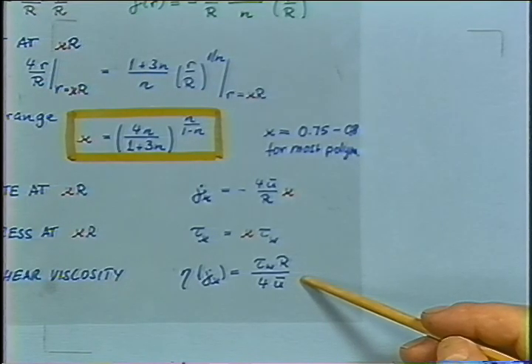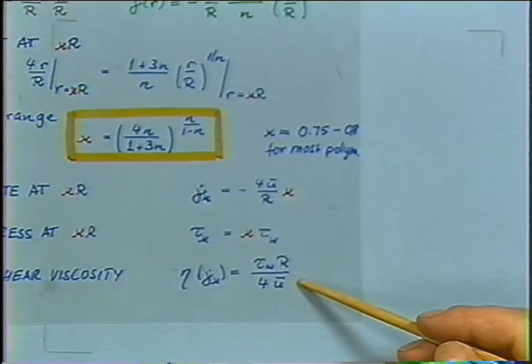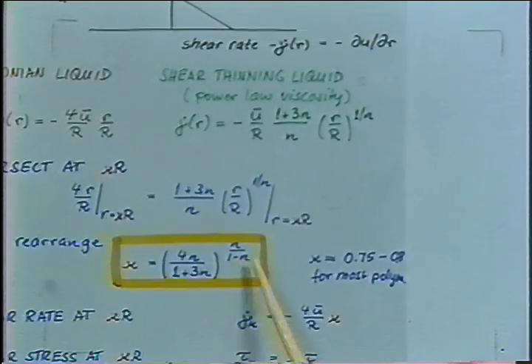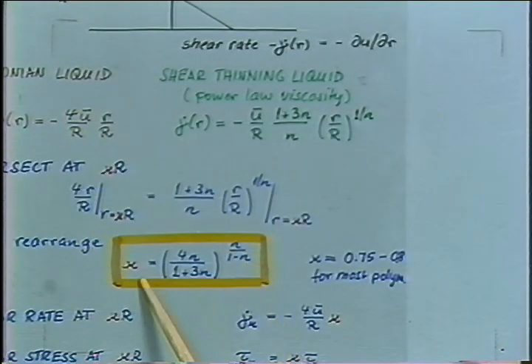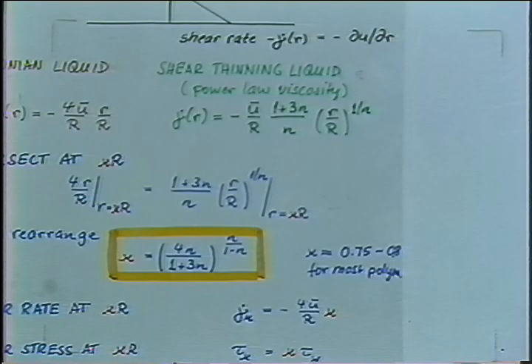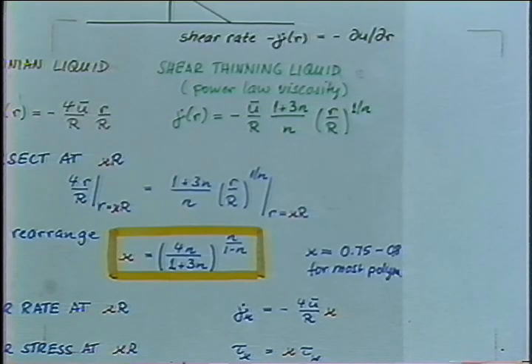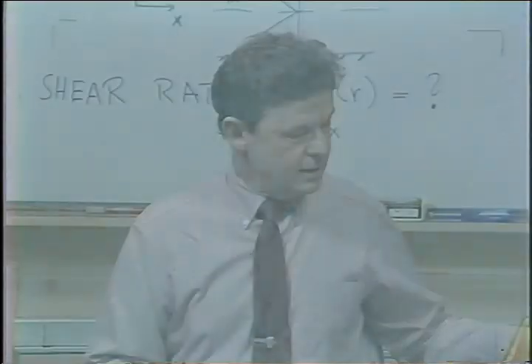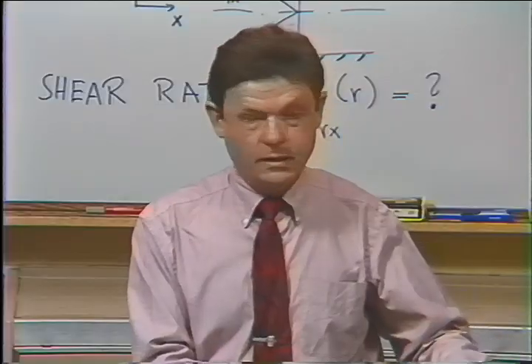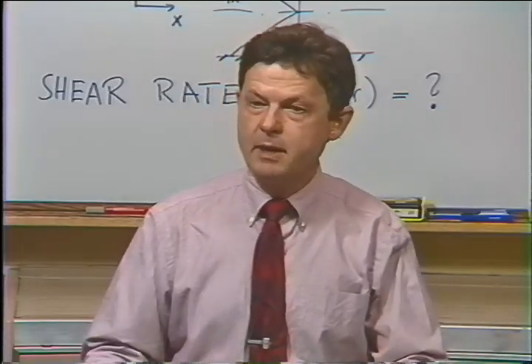Now, there's still some error involved because you didn't know kappa in detail, but if you do this for your sample over a range of shear rates, you can plot your viscosity function now, determine your power law exponent. You get an improved value for n. You get an improved value for kappa, and then in your second iteration, you have a very good value already for the shear rate, and then for the viscosity. So with this technique, you could immediately get viscosity data from a capillary flow experiment.